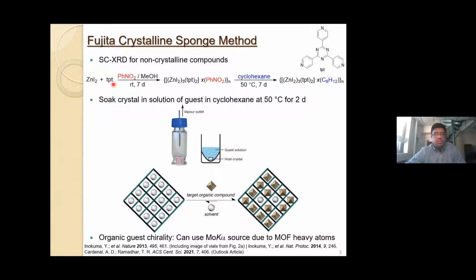TPT. TPT being the ligand, which is tris-4-pyridyl-1,3,5-triazine. And so in order to grow these crystals, what you do is you solubilize the TPT ligand in nitrobenzene, and then you layer on top of that a solution of zinc iodide in methanol, and then you let that sit at room temperature for 7 days, and then you're able to isolate crystals that are at the interface of those solvents. And then the next thing that you have to do is to exchange out the nitrobenzene for cyclohexane.